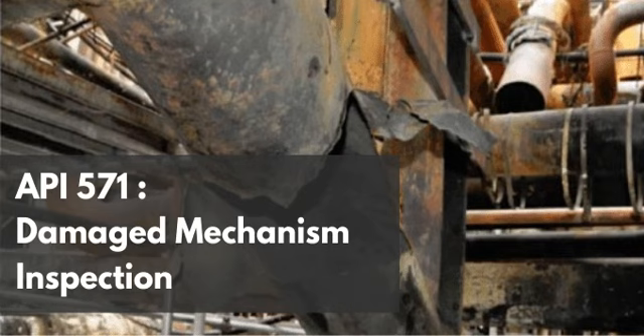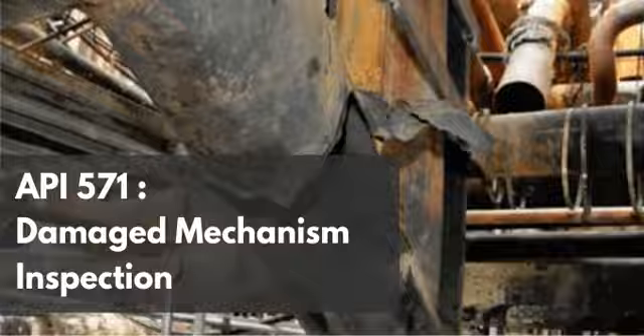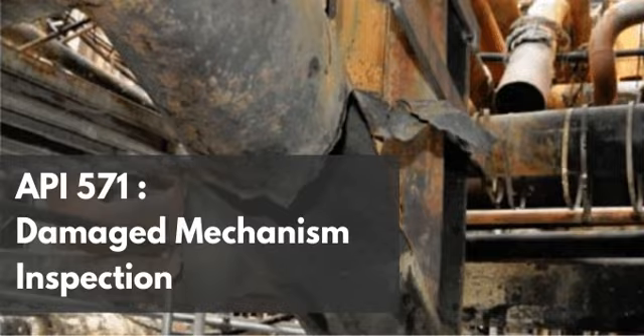To find it, inspectors rely on non-destructive testing, or NDT. And there's a very specific NDT method utilized for this. Field data points out that this specific type of highly localized weld damage was historically identified using shear wave UT, or ultrasonic testing inspection. Yes, shear wave UT. It's a staple of refinery inspection. But this raises an important question regarding how that UT data is actually interpreted by the technician in the field, because the reality of this damage mechanism reveals a terrifying inspection paradox.